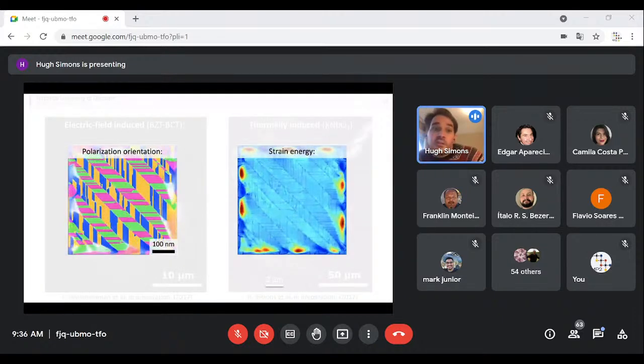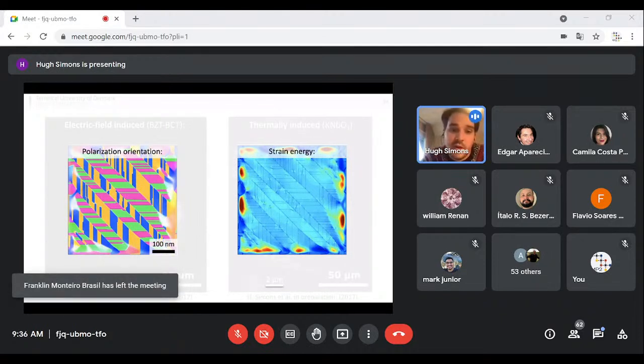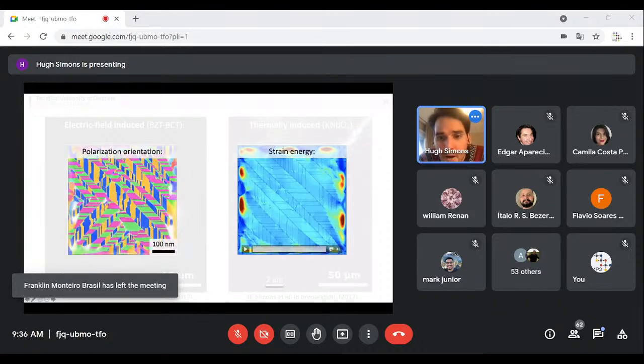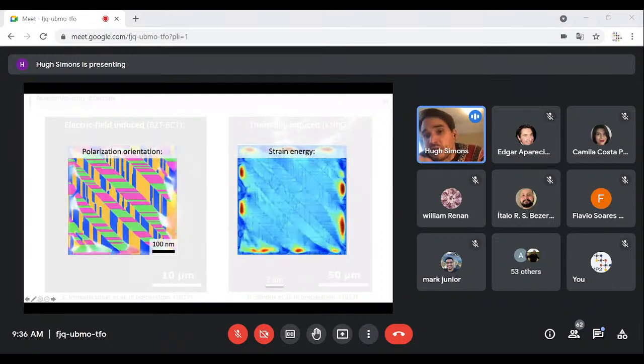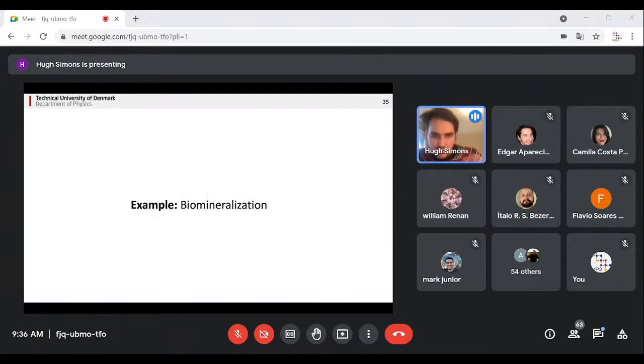And this is really nice because this gives us an opportunity to correlate with, for example, in particular phase field models. So in ferroelectrics, one of the leading modeling techniques is a thermodynamic modeling tool called phase field modeling. And this can predict, for example, the strains and the polarization and orientation relationships between neighboring domains. And so by carrying out these types of simulations in the same conditions and comparing the values to our experiment, we really have a nice way both to validate the models and also to guide us into new ways of engineering these materials.